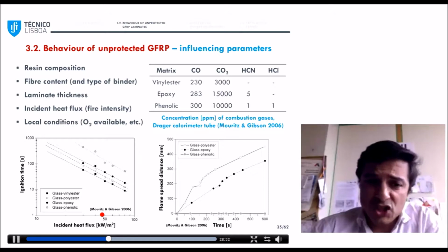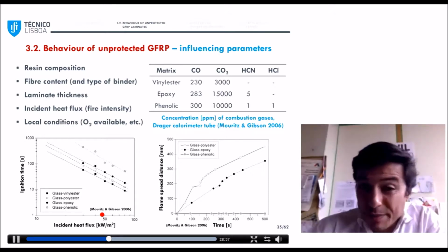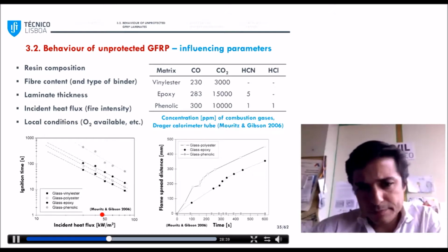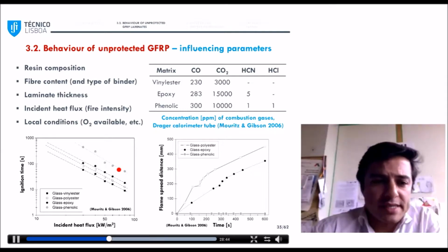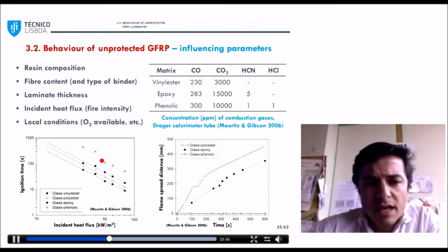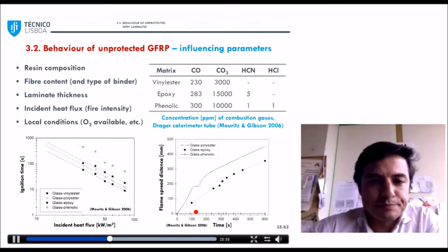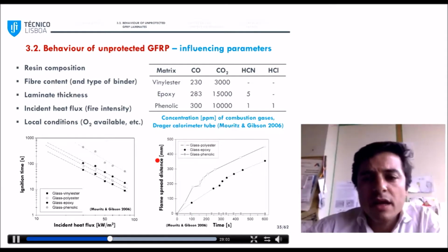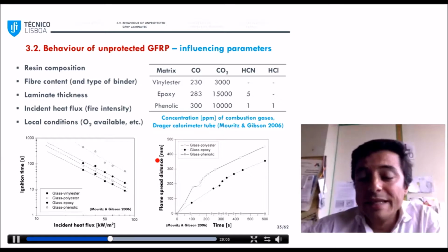This left picture here shows the time to ignition for different resin systems as a function of the heat flux. You can see that the ignition times are quite low, so this shows the flammability of current resins. And you can also see the much better performance of phenolic resins, so these gray dots. This better performance is also reflected in the right plot, the flame spread distance as a function of time, which is 0 in phenolics.